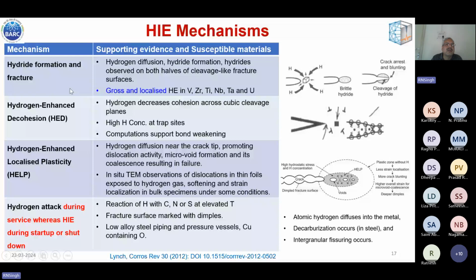Now, the second mechanism, hydrogen enhanced decohesion. This is observed mostly in iron and steel. Here hydrogen decreases the cohesion across certain cubic cleavage planes. High hydrogen concentrations are there at the trap sites. Computational works also support this kind of bond weakening. So here again, suppose there is a notch, first hydrogen accumulation will take place, that will weaken the bond and the crack will grow through that.